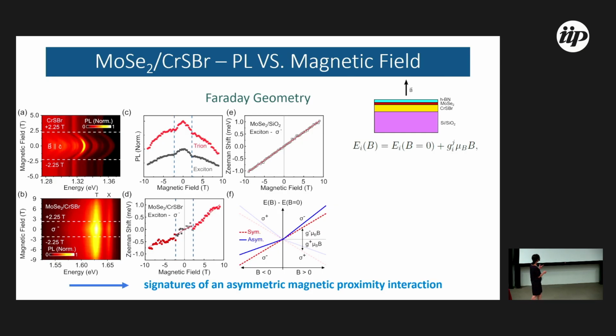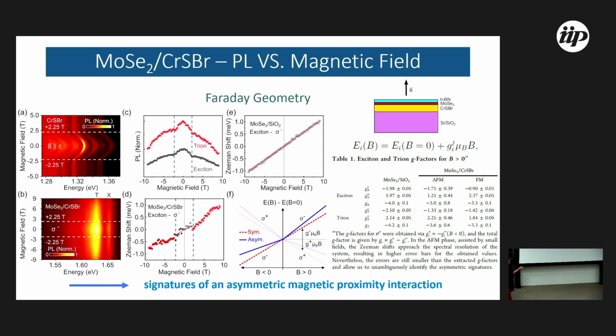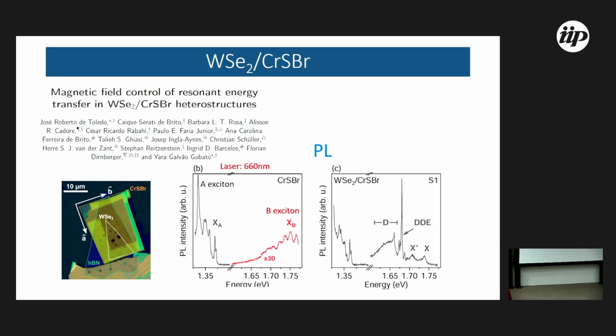This asymmetric proximity interaction was observed for one 2D magnetic material previously. You can see it clearly, because if you put MoSe2 on SiO2, it's linear, one slope only, and here we have different slopes, so different g-factors. Here we extract the values. Okay, there are a lot of things here, but I can go faster.